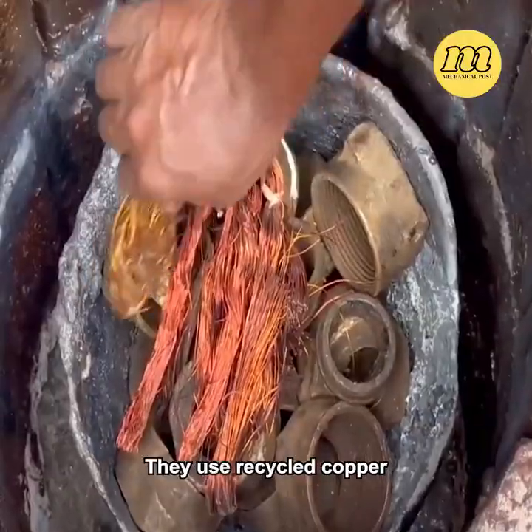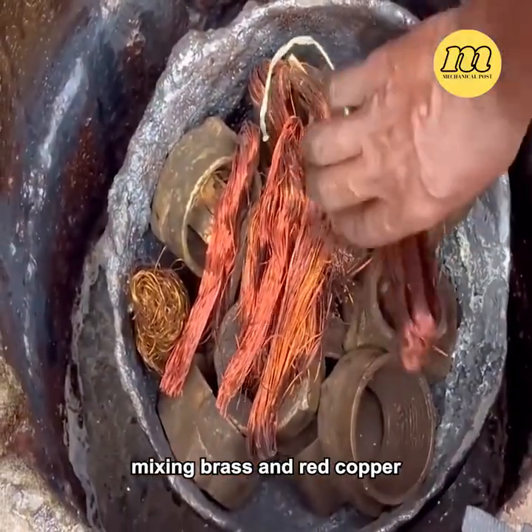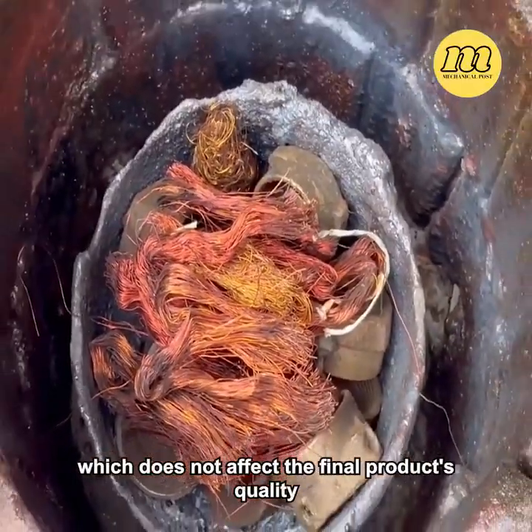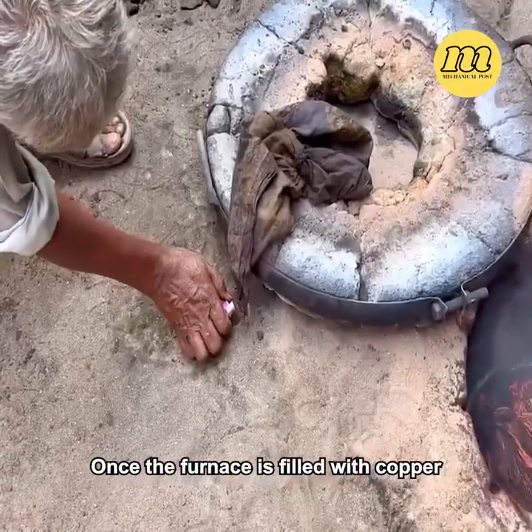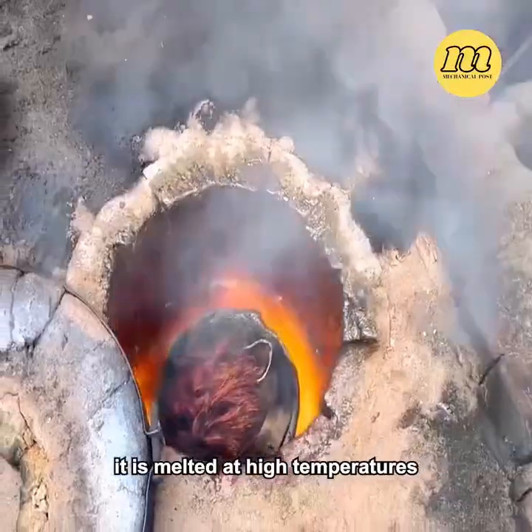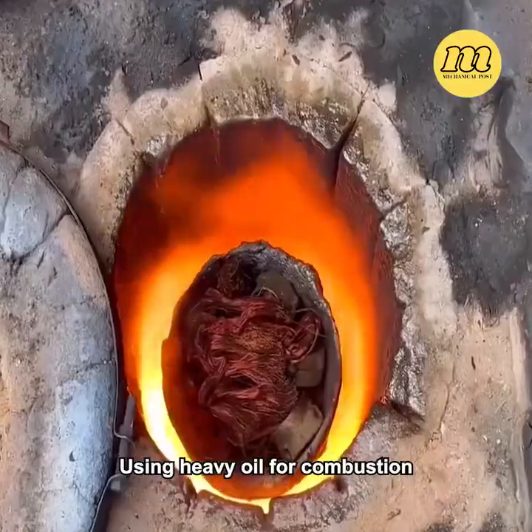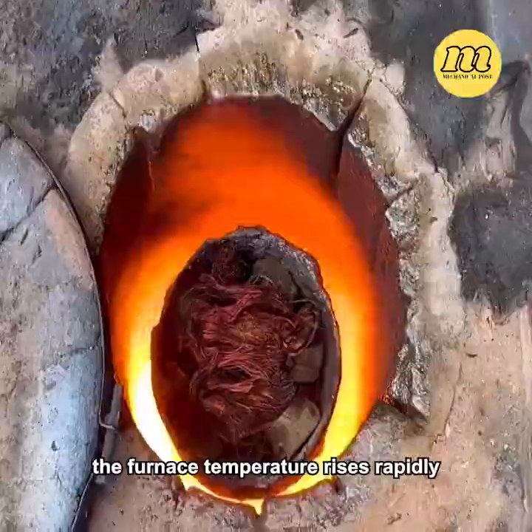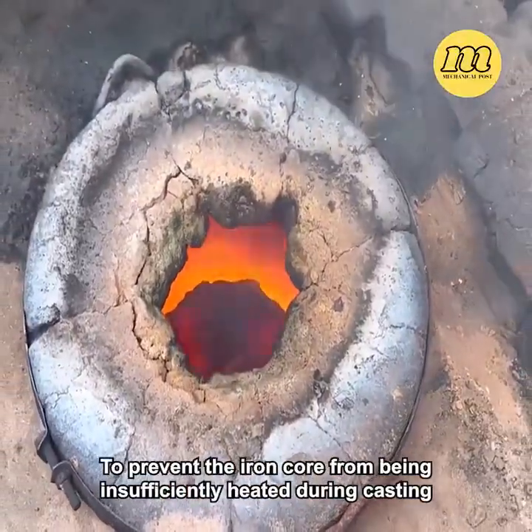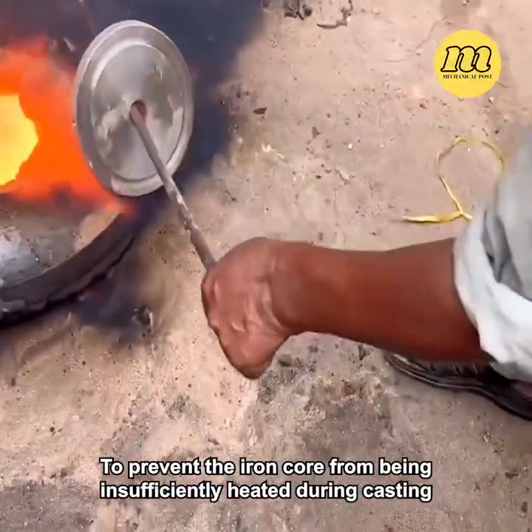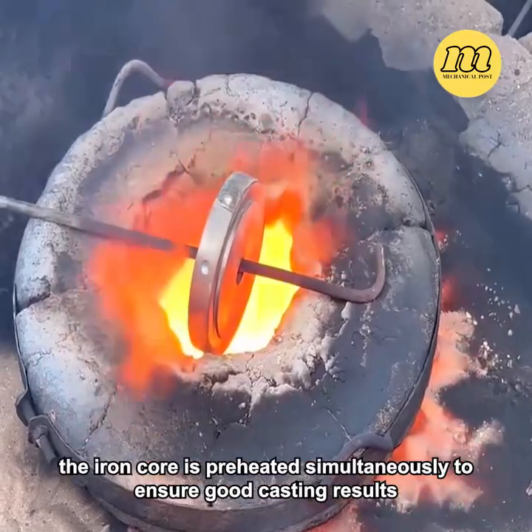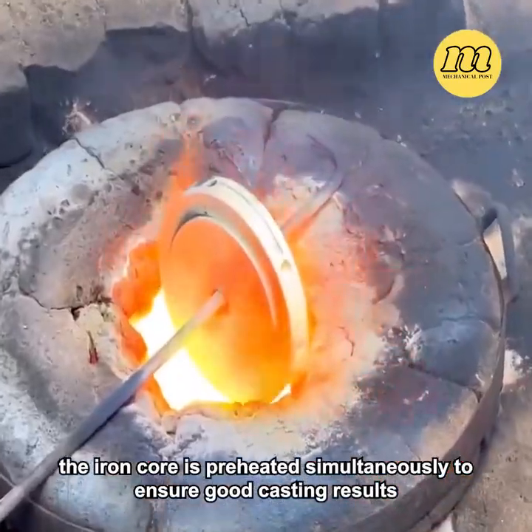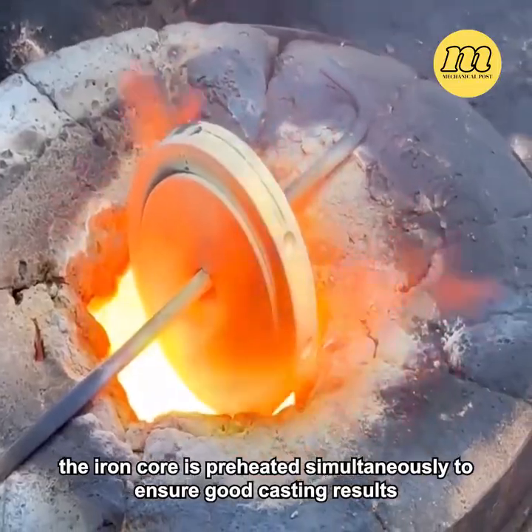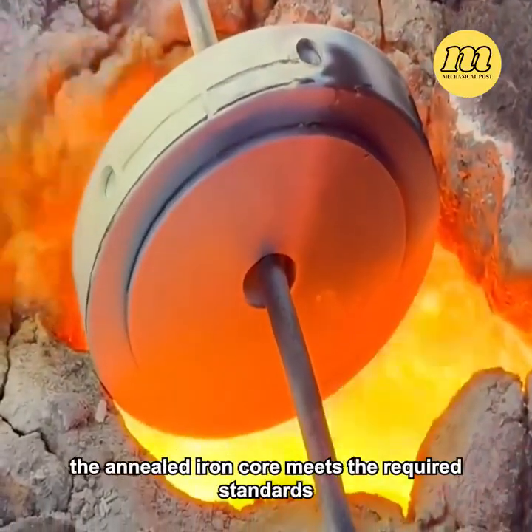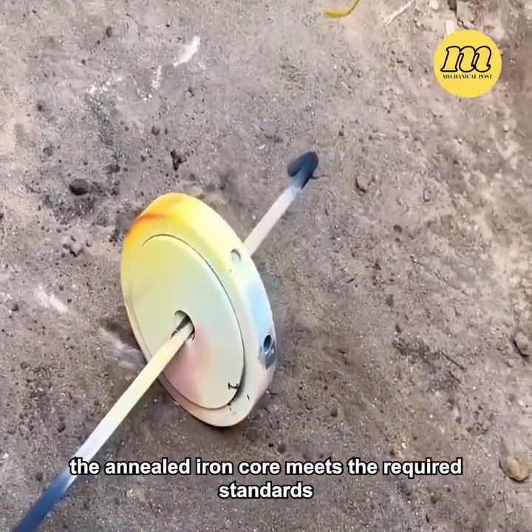They use recycled copper, mixing brass and red copper, which does not affect the final product's quality. Once the furnace is filled with copper, it is melted at high temperatures. Using heavy oil for combustion, the furnace temperature rises rapidly. To prevent the iron core from being insufficiently heated during casting, the iron core is preheated simultaneously to ensure good casting results. After 10 minutes of heating, the annealed iron core meets the required standards.